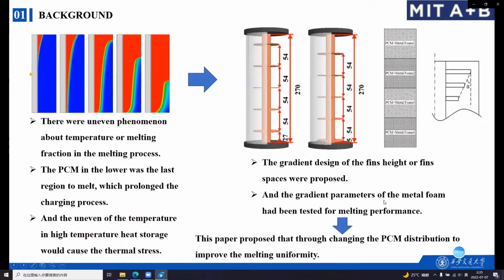But there was one problem during the melting process: the melting performance was uneven. The PCM in the upper region melted faster than the PCM in the lower region, and the PCM in the lower region prolonged the full melting time. Additionally, the unevenness of the temperature in the high temperature heat storage would cause thermal stress, which will affect the use of heat storage.